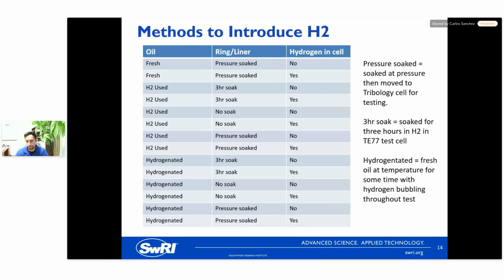We also looked at either bubbling hydrogen or pumping hydrogen through the oil. So in this case, putting the inlet port at the bottom of the chamber to where the hydrogen comes through the oil, versus having the inlet port at the top of the chamber where it just saturates the environment where the parts are sitting in. So within all those different methods, we found that soaking the parts in hydrogen for 3 hours prior to running the test, and then having the hydrogen actually flow through the oil during the test caused the most severe cases. So that's one of the things we're looking at.